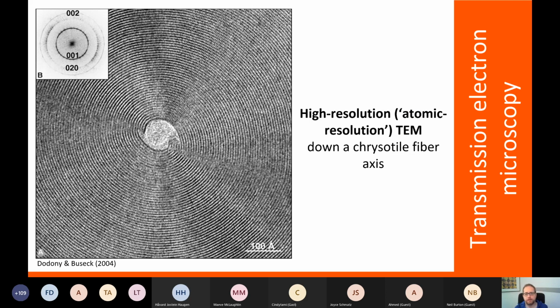Lastly, we can go to very high resolutions, and I won't go into detail here in this lecture, but you've seen already one picture of these gold atoms. We can go to high resolution phase contrast imaging, where we can now look at materials such as this one here. This is a chrysotile fiber. This is a serpentine. It actually has a tiny gap in the middle here, and you can study the atomic configurations within this mineral, and the distance, for example, between these layers here tells you something about the real distance of your crystallographic spacing.